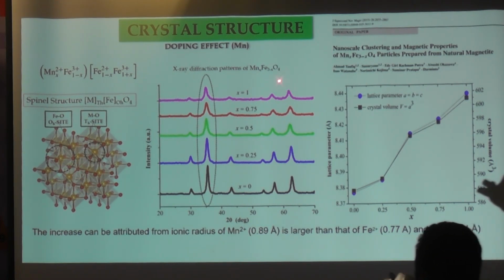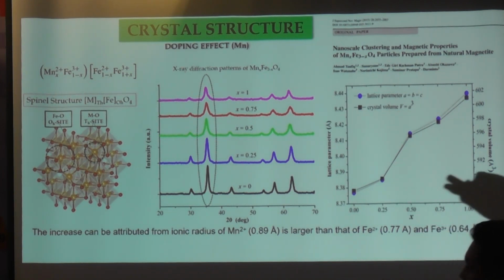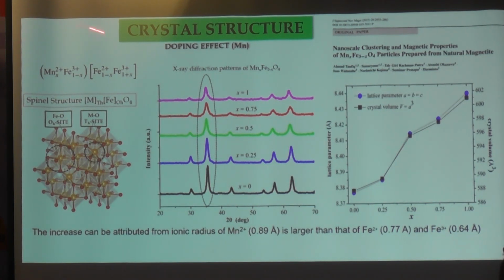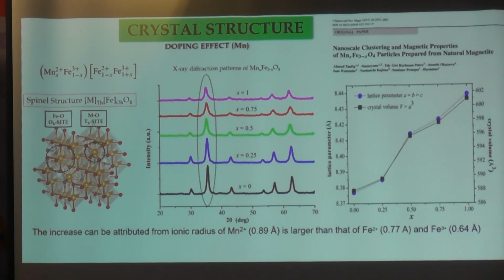So where is the Mn or iron in here? We can make a theoretical formulation using a chemical equation that guarantees manganese replaced iron in the tetrahedral position, because we know the spinel structure is a cubic structure. We know the a, b, c lattice parameters are the same, and the angles between x, y, z are 90 degrees. So in the spinel structure there are two subsystems. The first one is the tetrahedral site and the second one is the octahedral site. So the manganese ion replaces the Fe ion in the tetrahedral position.